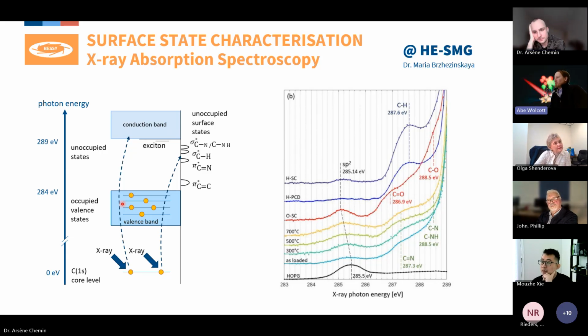The only thing that I view as controversial in my mind is that alcohol peak at 288.5 eV. My group has basically taken alcohols off, put them back on, put in silica shells, put in nitrogen on the surface, and that pre-edge feature at 288.5 does not readily change with alcohol-rich diamond versus non-alcohol-rich diamond. I'm curious if you've ever done any calculations on this, because I just don't believe the 288.5 eV feature is alcohol specific. It could be something else, maybe based on an oxide, but I find that the alcohol sigma star CO is above our band gap and above our diamond hole exciton. So I'm really waiting for somebody to do some calculations on it. Do you have any comments on how that feature is changing?